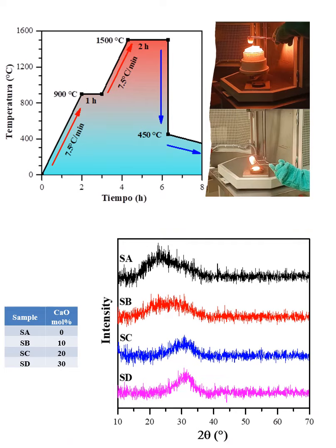In this work, the synthesis was carried out using the melt-quenching technique. In the process, precursors were placed in a platinum crucible and melted at 1500 degrees for 2 hours. The melted samples were quenched on a preheated stainless steel plate at 450 degrees, with subsequent cooling at room temperature.